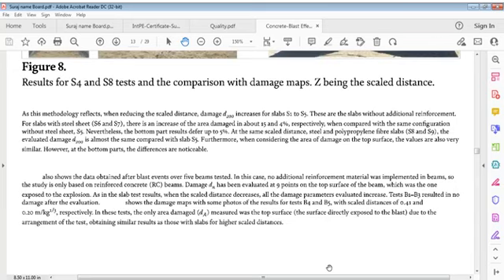For slabs with steel sheet, there is an increase in the area damage of about 15 and 4% respectively when compared with same configuration without steel sheet. Nevertheless, bottom part results differ by up to 9%. The same scale distance steel and polypropylene fiber slabs.